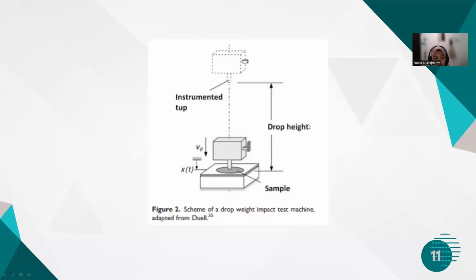And drop height: the vertical distance between the initial position of the impactor and the top surface of the specimen. A higher drop height results in greater potential energy, which is converted to kinetic energy at the moment of impact. And lastly, the sample or test specimen, the material under test, which in this study is the composite reinforced with auxetic or conventional knit structures. The sample is placed on fixtures beneath the impactor.